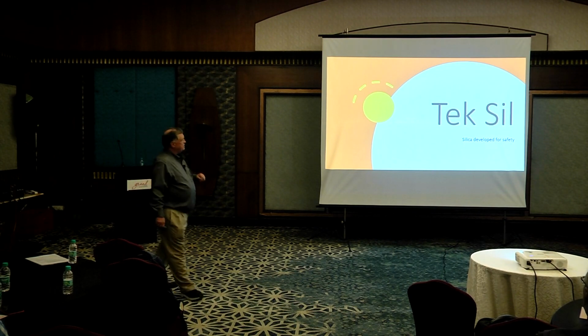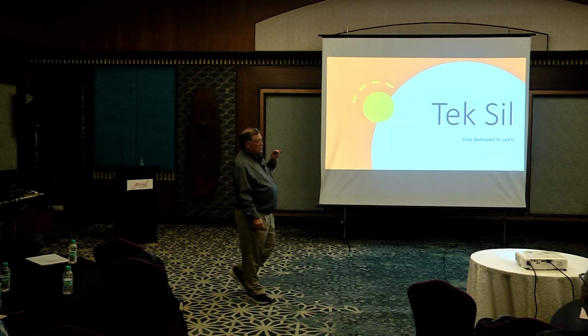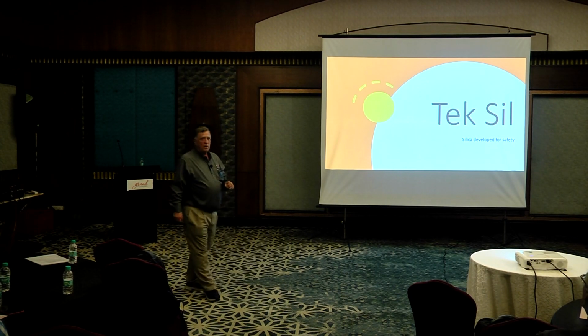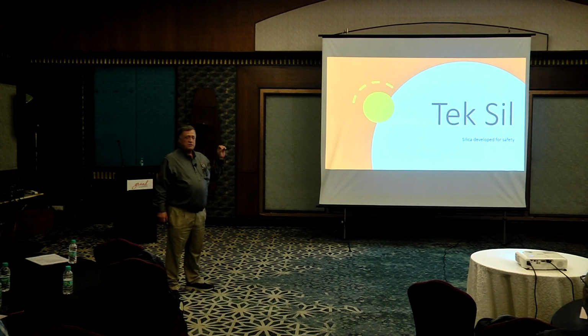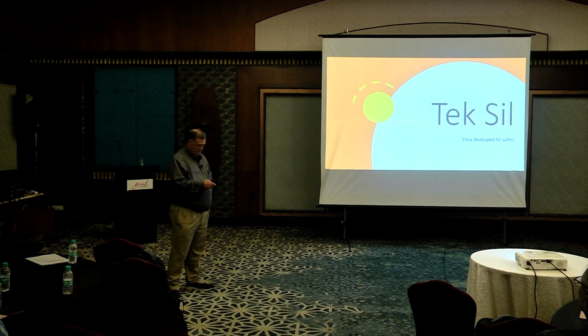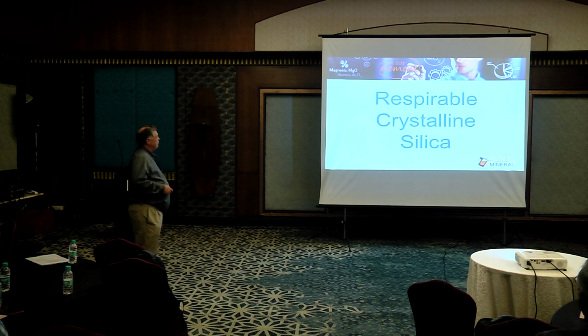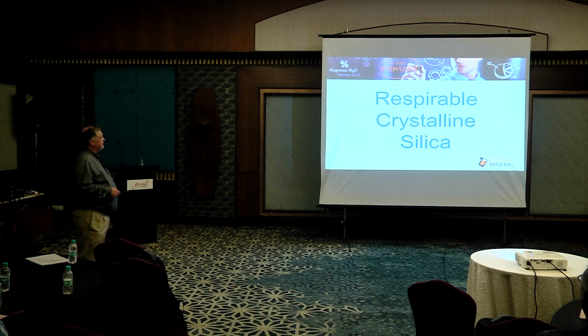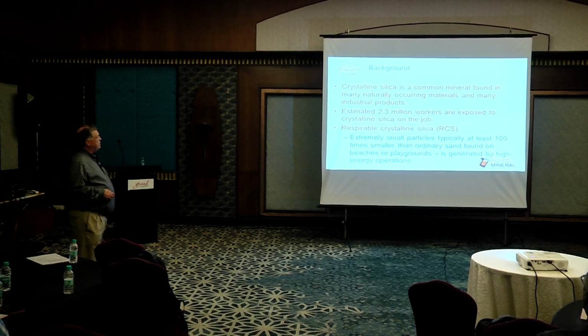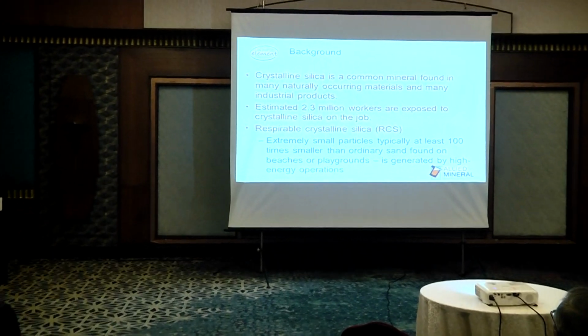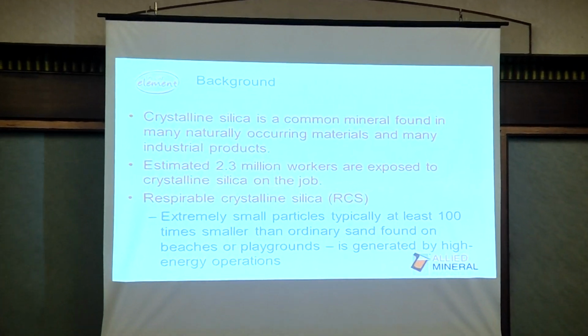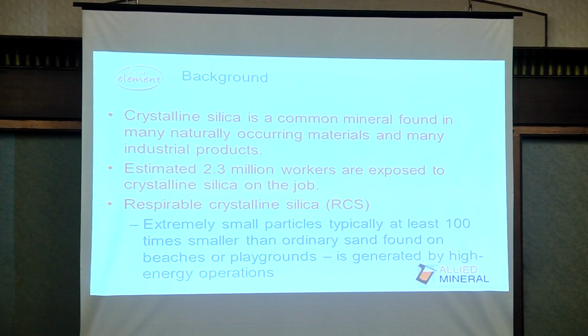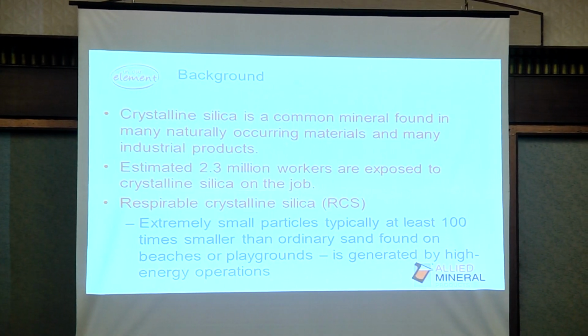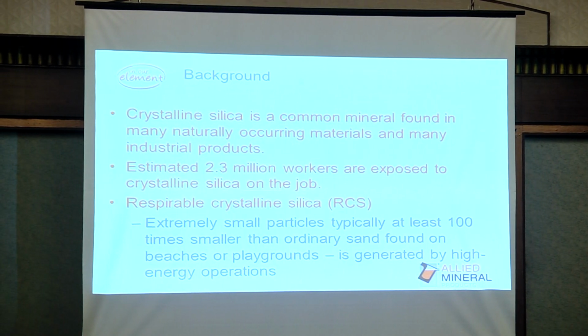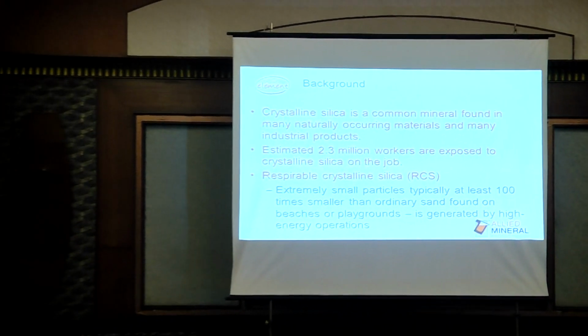So we've developed this product called Tek Sil. It's a silica with 99% lower respirable silica, meaning that as you're doing the installation, there's almost no harmful silica being breathed by the workers. Crystalline silica is a common material found in many naturally occurring materials. It's estimated that 2.3 million workers are exposed to crystalline silica on the job. It could be in a foundry, shot blasting, or processing companies. So there are a lot of different areas.